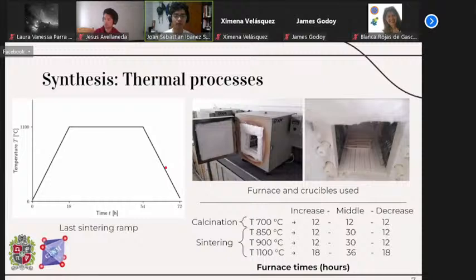Next, we proceeded to calcinate our sample at a temperature of about 700 degrees Celsius. This was in order to remove any extra water that we could have in our sample and to promote the production of carbon dioxide and decompose calcium carbonate on the pills.